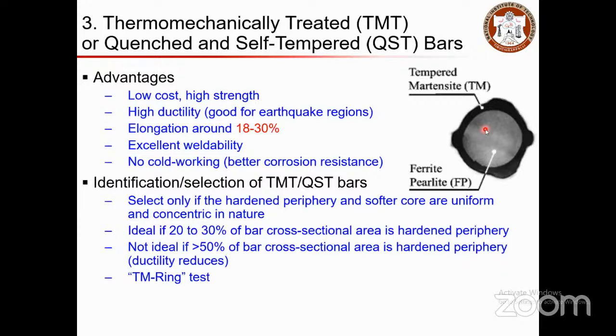Typically, when we talk about this hardened phase, the hardened phase here is the TM ring. The TM ring should ideally be about 20 to 30% of the total cross section, and then the inner section should be more than 60%, so that the ductility will be more. If it is not at the adequate level, then you may compromise the ductility. So these things can be identified using the TM ring test.